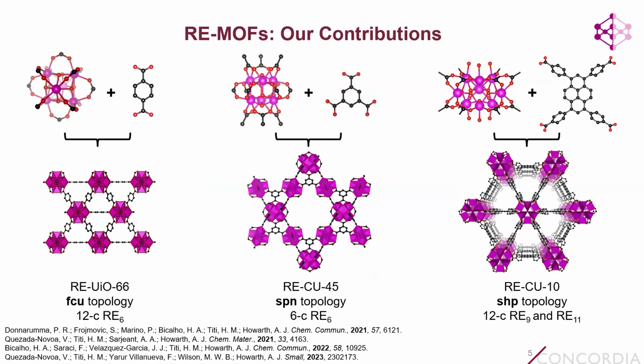So this MOF has these hexanuclear clusters that are 12 connected, bridged by the terephthalic acid linker, and the overall FCU topology. So Mohammed Eddaoudi and his research group had previously shown that you can make these clusters in situ, and they had shown some other MOFs with FCU topology, but our report in 2021 was the first example using just the regular terephthalic acid linker that's used to make UiO66.